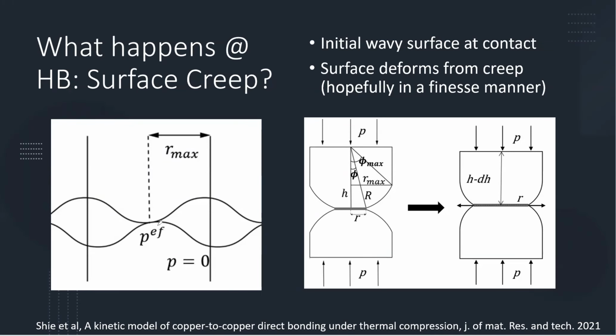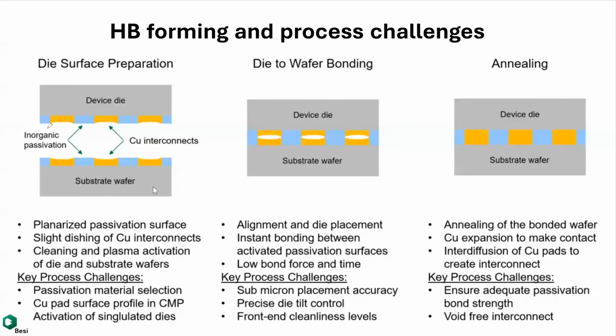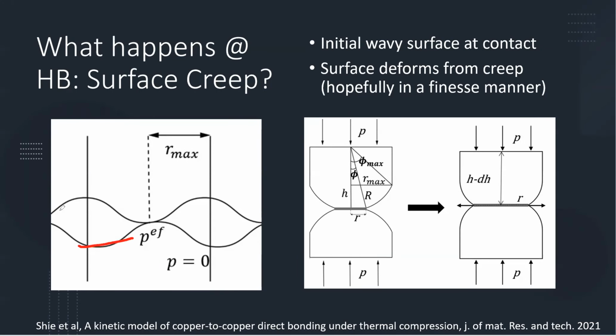What he did here is to simulate the process with a kind of sinusoidal wave, right? It's a wavy surface, as we show here. That's what he assumed because he needs to mathematically simulate it, right? And here the cavity will be forming like this. That's the void. And then you have a contact start to form, right? And then this is the copper starting to bond here, and then you squeeze the copper pillar to squeeze out.